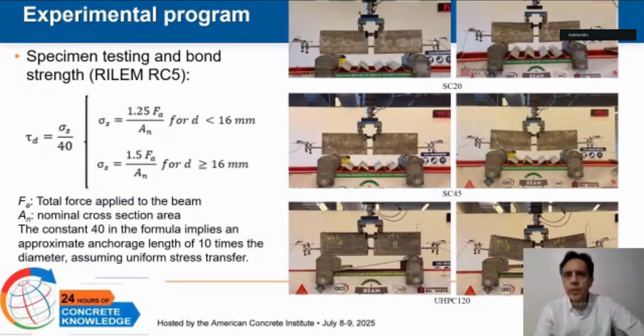This slide presents the visual results of the bond strength tests conducted on GFRP reinforced specimens using the RILEM RC5 configuration, alongside the formulas used to calculate the bond stress. On the left of each pair, we observed the unloaded, undamaged beams in the testing frame. On the right, we see the condition of the same specimen after failure, revealing the distinct failure mechanisms associated with each mix.